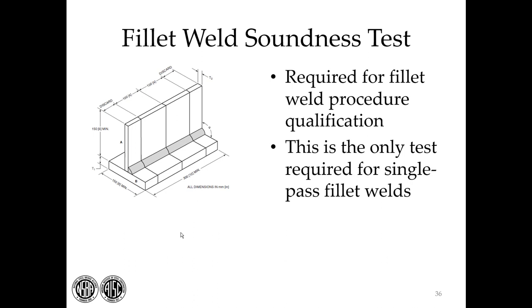For fillet welds, if you have a single pass fillet weld, then you only have to do this test. If your fillet weld is multiple pass, under the current code, you have to do a groove weld test as well. But for single pass fillet welds, and most of the fillet welding we do is made in one pass only, you have only this test plate.